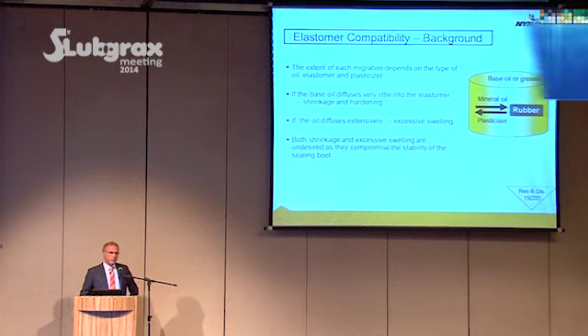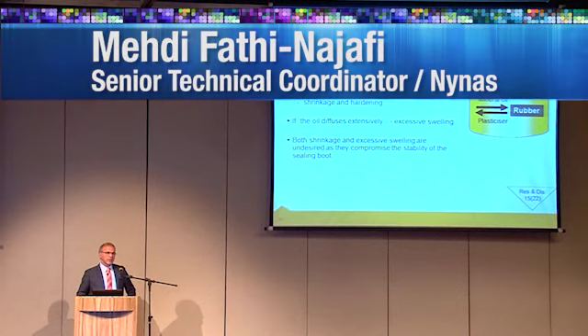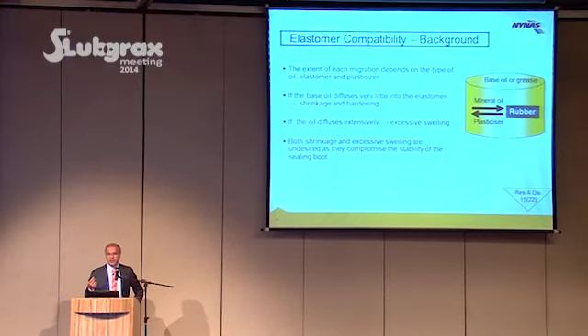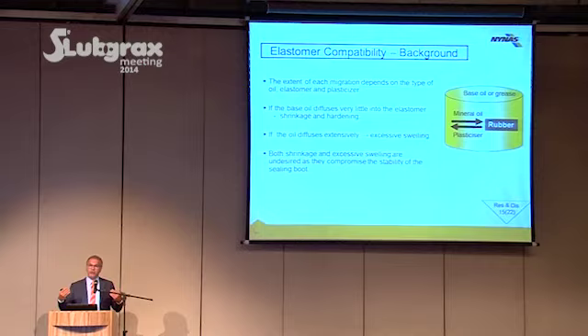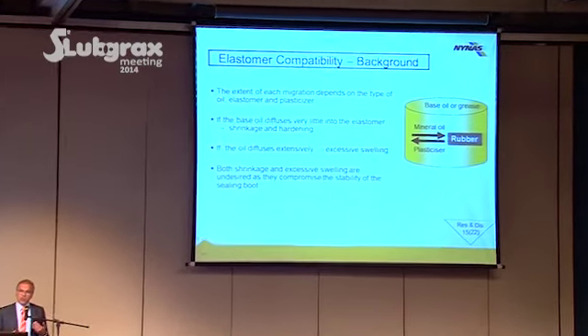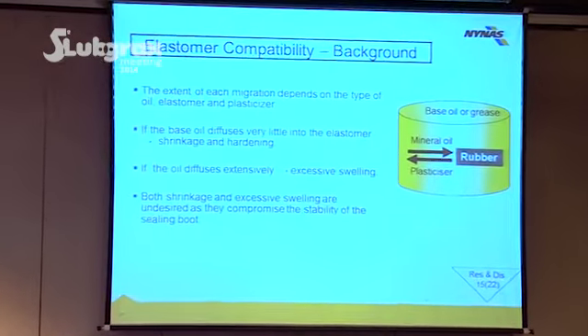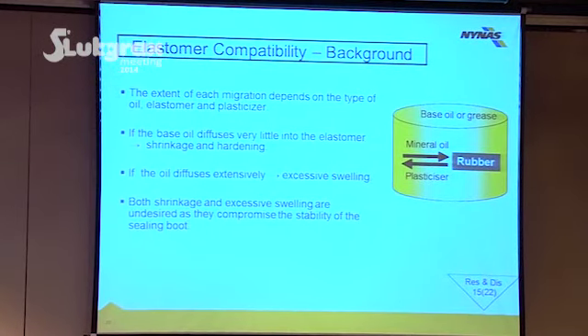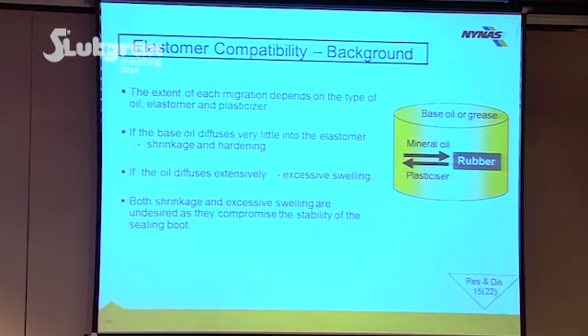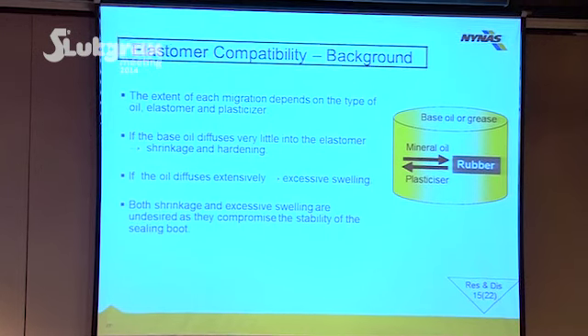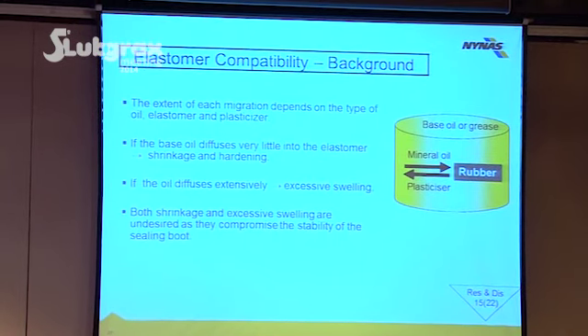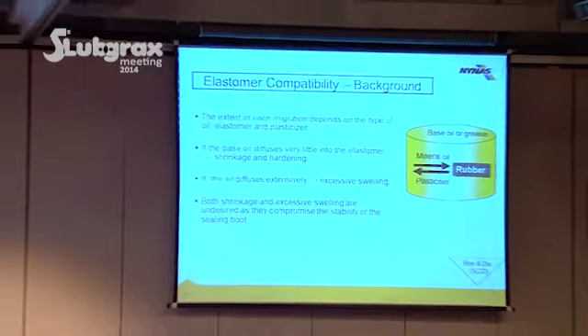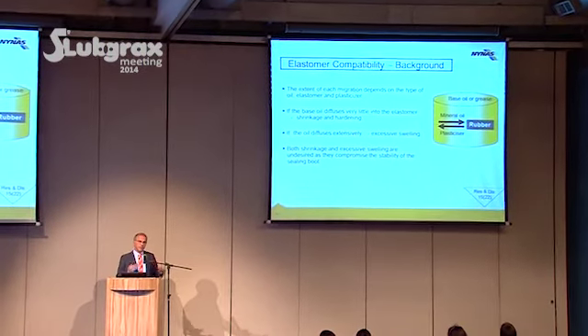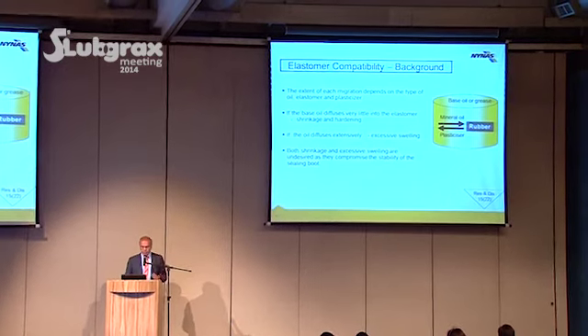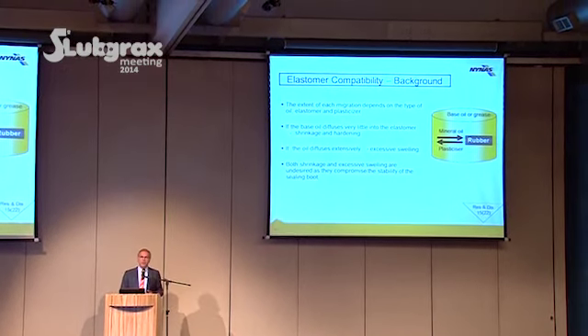I mentioned the automobile industry, for instance, CV joints. One of the tests is elastomer compatibility. There is a standard. The mechanism is not so complicated. Mineral oil migrates into the rubber, and consequently plasticizer, for instance, is pushed out from the rubber. The consequence is that you get a softer or harder rubber. The weight will change because the density of oil is very often lower than that of the plasticizer. So these are very important to the OEM.